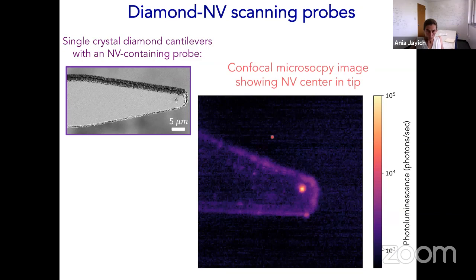If we take a confocal fluorescence scan of one of these probes and measure the fluorescence as we scan the laser, we see fluorescence from a single NV center in this pillar, emitting photons at the rate of about 100,000 photons per second, which is fairly bright, and thus makes it easy to see with a pretty simple, almost off-the-shelf confocal microscope.